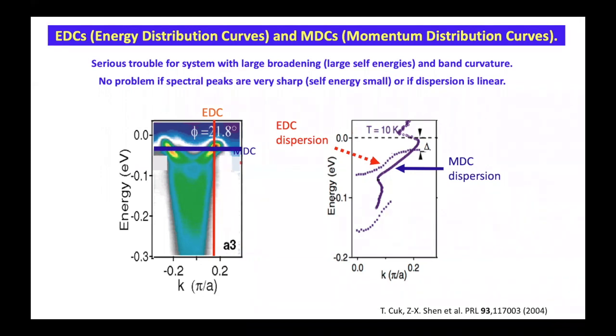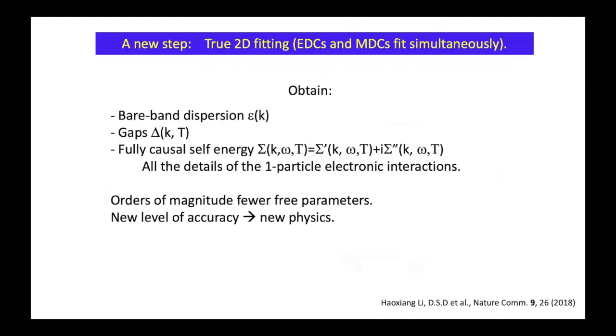So this is where the state of the art was until this past year, where we realized we need to go beyond 1D analysis and do a full two-dimensional analysis, dealing with both MDCs and EDCs simultaneously. And from this, we obtained the bare band dispersion, gaps, and a fully causal self-energy. We get sigma prime and sigma double prime simultaneously. So we're getting these details of one-particle electronic interactions. We're actually doing it with fits that have orders of magnitude fewer free parameters.